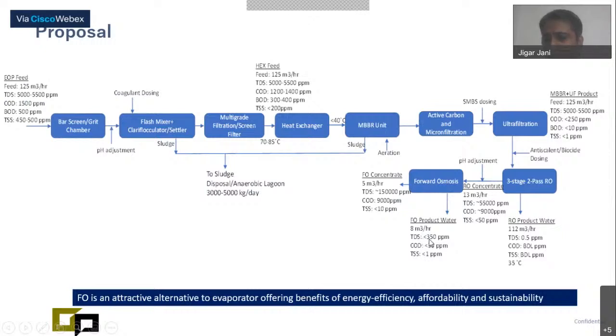The TDS is less than 350 ppm, and the final concentrate of the entire process will have a volume of 5 cubic meter per hour, with TDS of 1,50,000 ppm, 15% salt. So this concentrate, very minimal brine, can be sent directly to the dryer system or the solar pond, and we will have a very sustainable and effective process for the entire IDP filtrate.